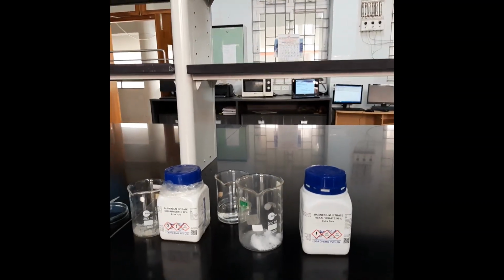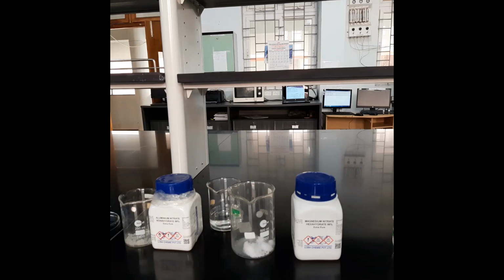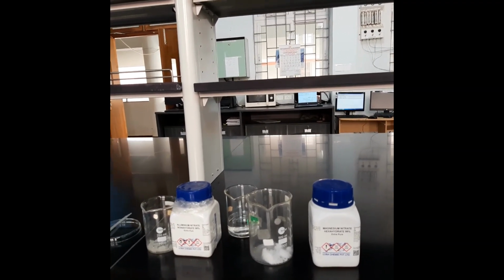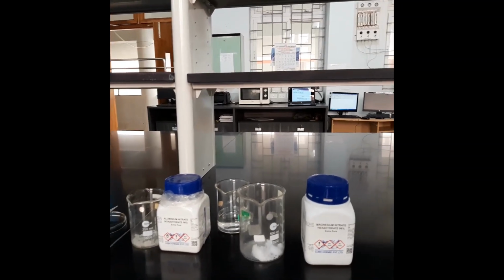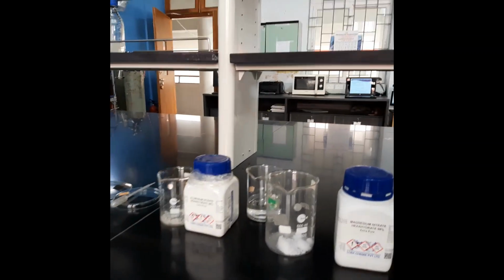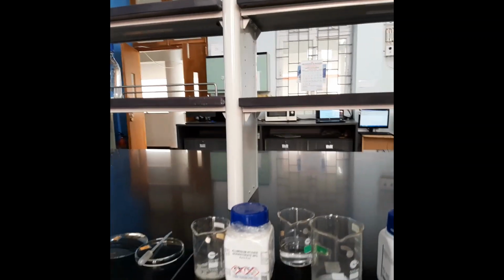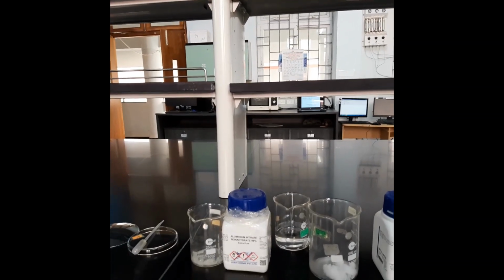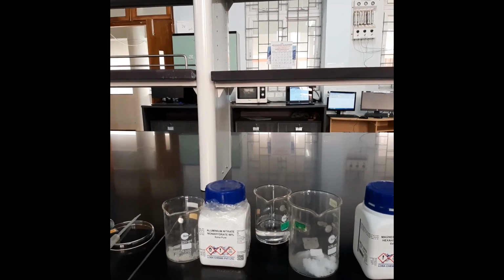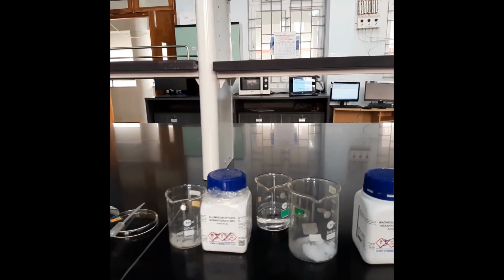Basically we know that the composition is 3:1 magnesium to aluminum. The magnesium should be 3 parts, that is 40 millimole we are taking, and aluminum will be 13.2 millimole. So the compound we are going to synthesize is magnesium aluminum hydroxide. So we have taken magnesium nitrate and aluminum nitrate.